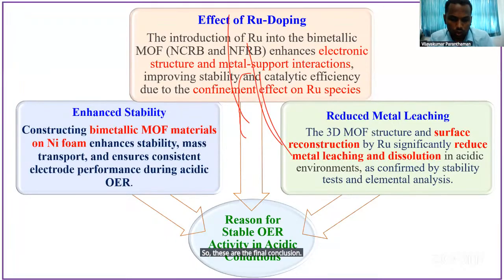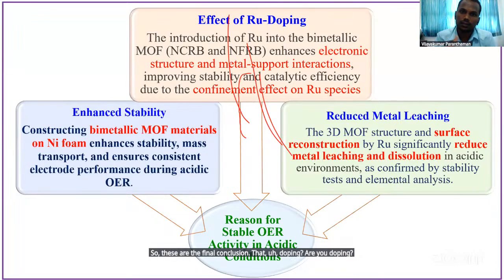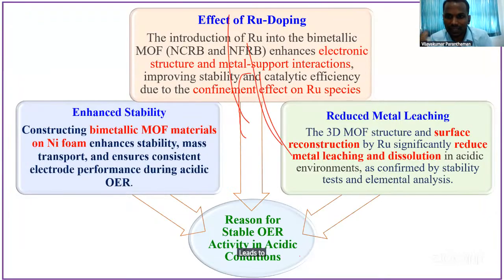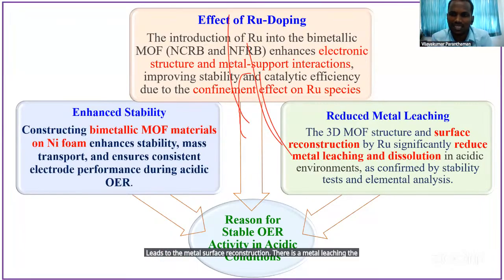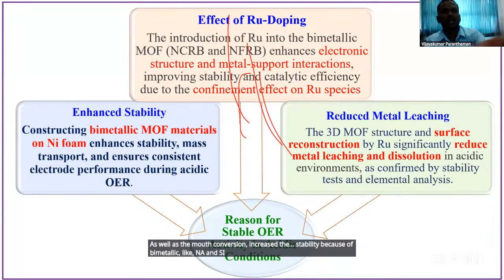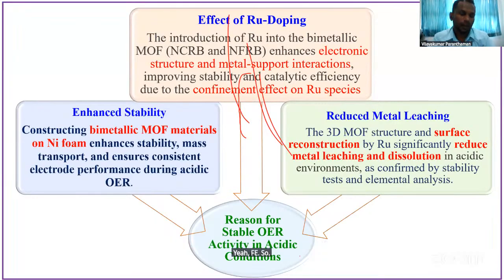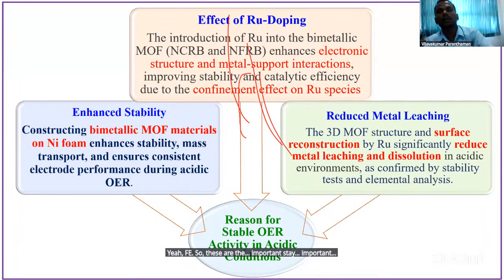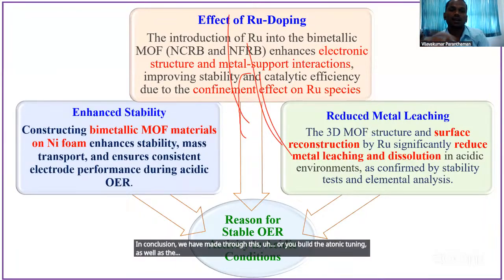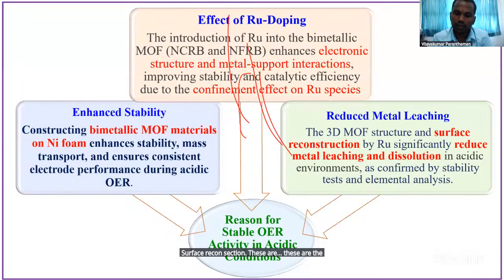The Ru doping leads to the metal surface reconstruction. That is the metal leaching, the dissolution, avoiding the metal leaching and dissolution, as well as the MOF conversion, increases the stability because of the bimetallic nature, like Ni and Co and NiFe. So these are the important conclusions we have made, through this Ru, the electronic tuning as well as the surface reconstruction. These are the achievements that have been made.